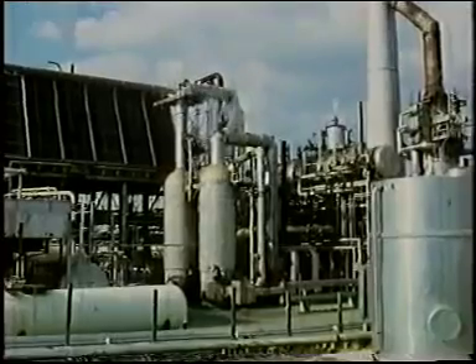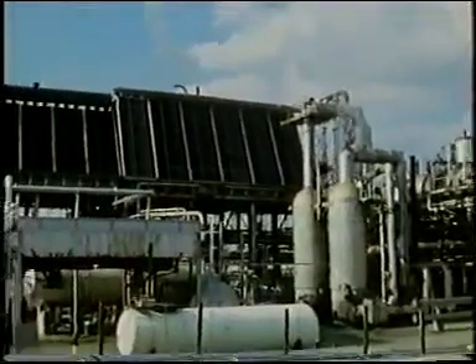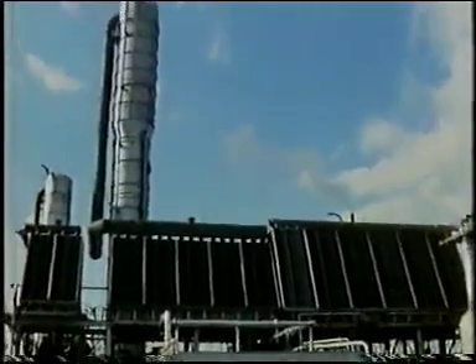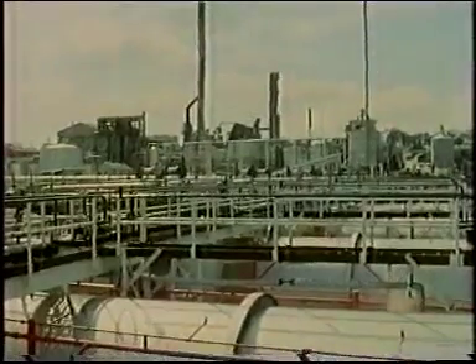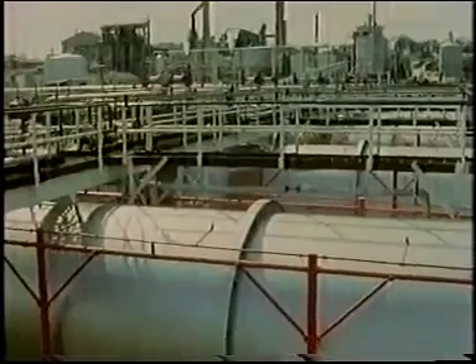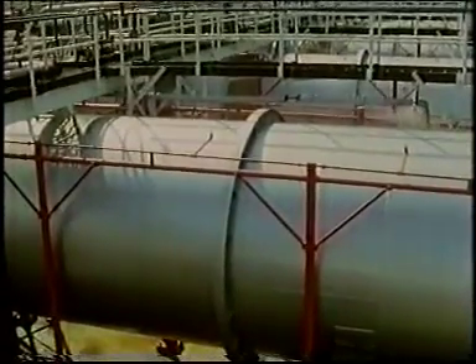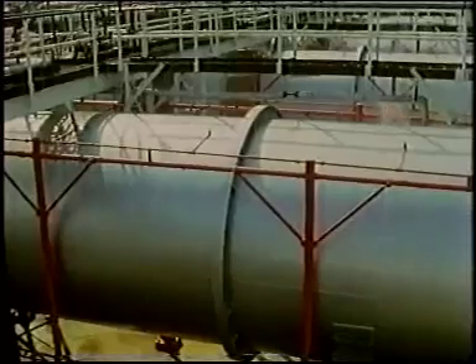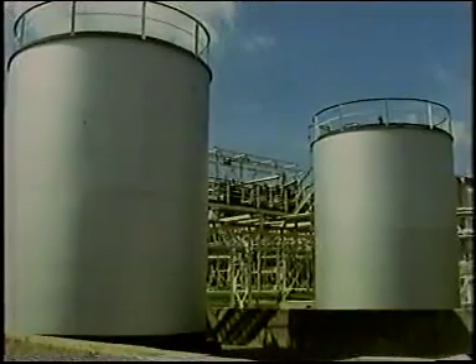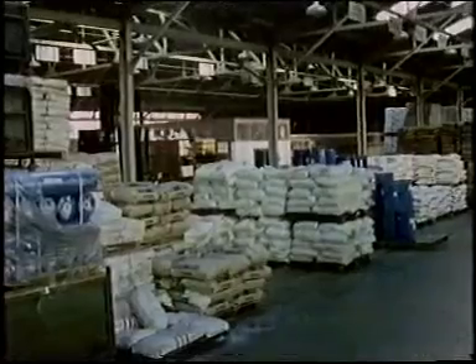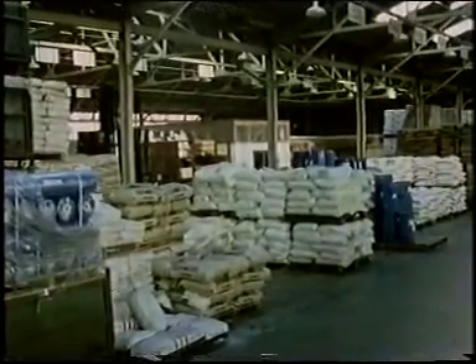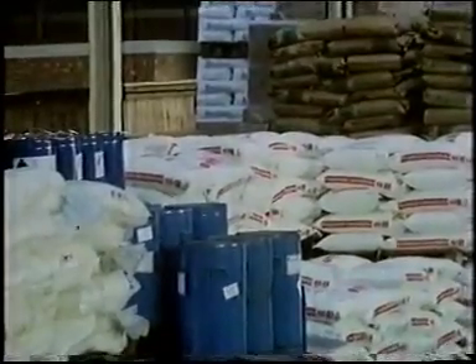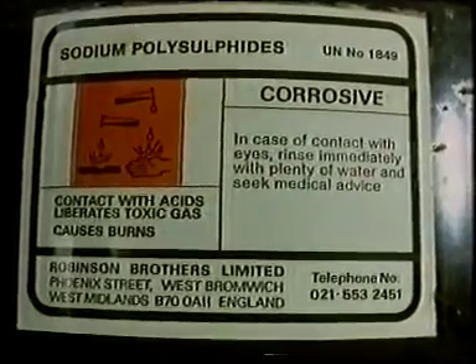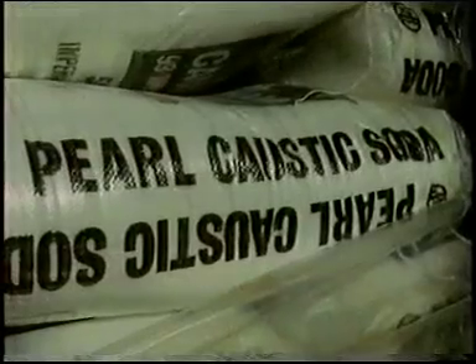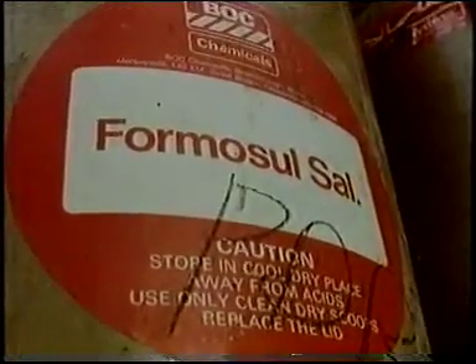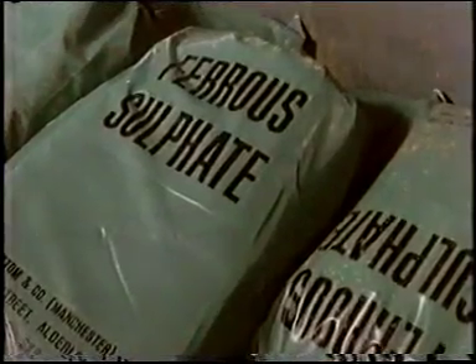Phenylethane is itself a feedstock from which the styrene monomer will be synthesized in this plant. The product is purified by distillation in fractionating columns. Butadiene is kept on site in pressurized tanks. The styrene is also stored here. Styrene and butadiene are not the only raw materials. It takes many more secondary ingredients to feed the SBR process. Agents to initiate polymerization, to control chain length, prevent oxidation, and to terminate the reaction when it's gone far enough.